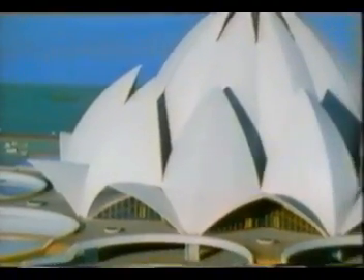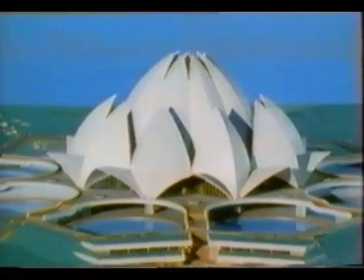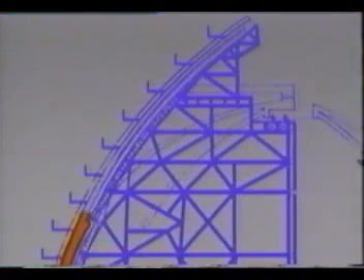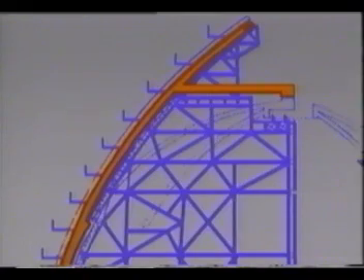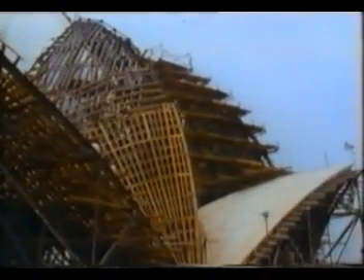For aesthetic and structural reasons, Mr. Sahba was determined to avoid construction joints in the shells. This required finding a way to pour the thin 13-centimeter shells up to 22 meters high in one continuous operation. This was more than 10 times the maximum height of pour recommended by the consultants. Pouring to such heights and compacting concrete in the narrow forms, which for some shells was no more than 7 centimeters wide and curved in 2 directions, posed the most formidable challenge.